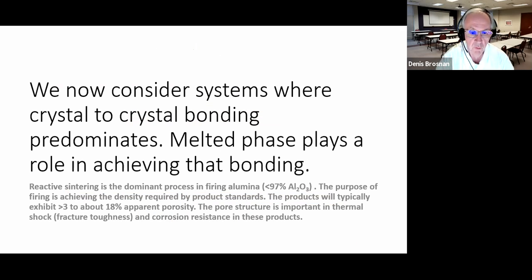Now, one of the differences between the past classes is that we're considering systems where crystal to crystal bonding predominates. Corundum, alumina crystals, corundum crystals to corundum crystals bond directly to each other in the systems we're talking about. The higher the percentage of alumina, of course, the more this comes into play. Melted phase can play a role in achieving some of that bonding, particularly when you're below about 97% alumina or thereabouts. When you're above that 97%, if you get to the 99%, melting phase is a secondary phase, not quite as important. However, we may use some techniques to create a slight amount of melted phase to help us in sintering.